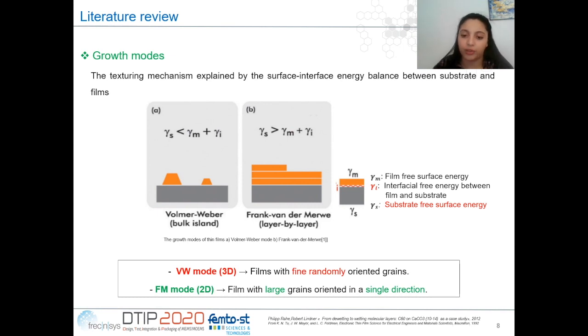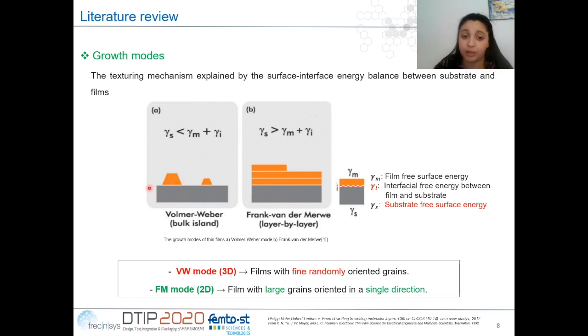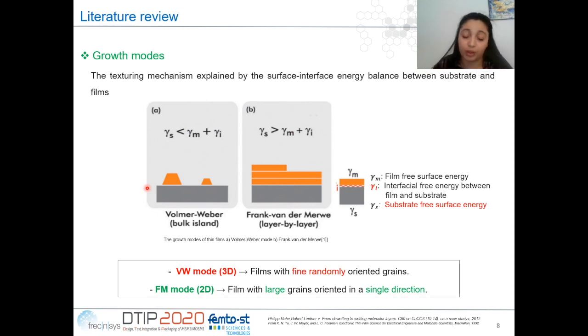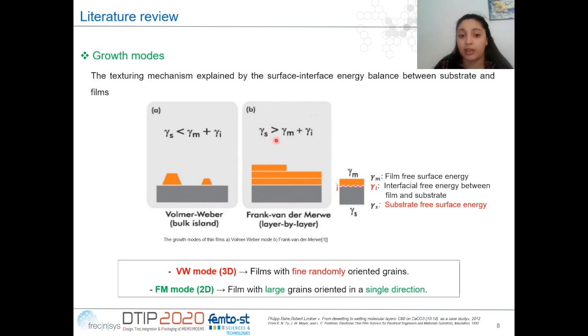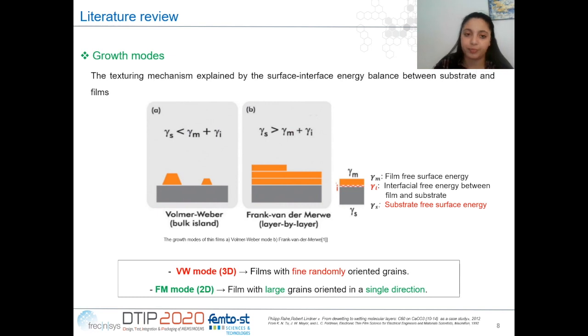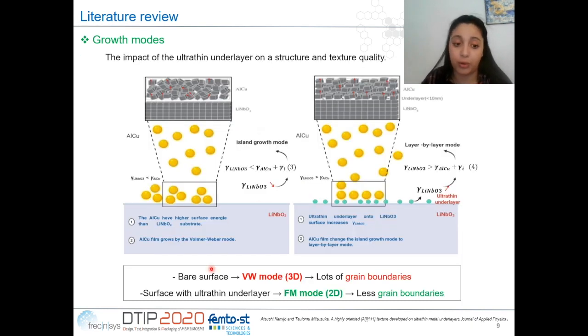In general, there are two kinds of growth mode. The Volmer-Weber mode, or island growth mode, occurs when the free surface energy of the substrate is lower than the free surface energy of the film — resulting in a film with randomly-oriented grains. In the opposite case, when the free surface energy of the substrate is higher than that of the metal film, the film grows layer by layer and we obtain a film with grains oriented in a single direction.